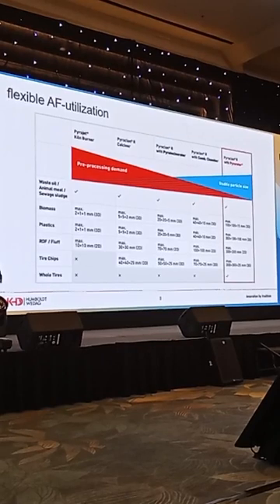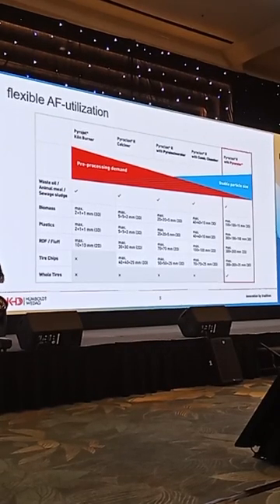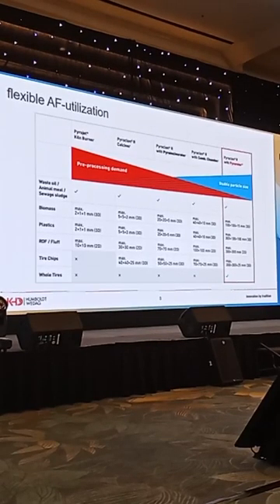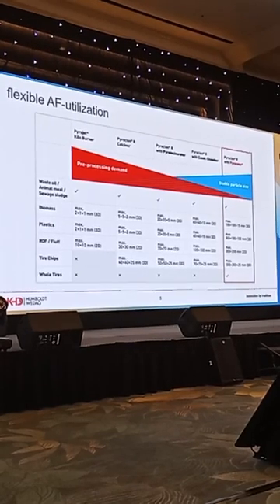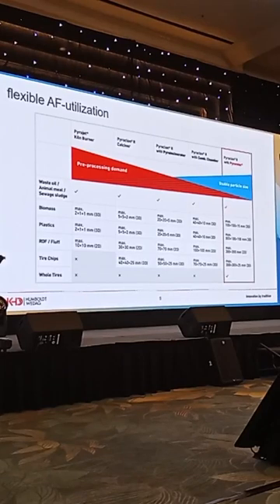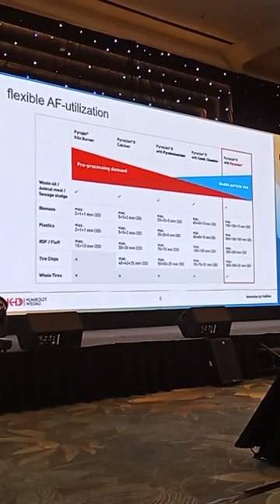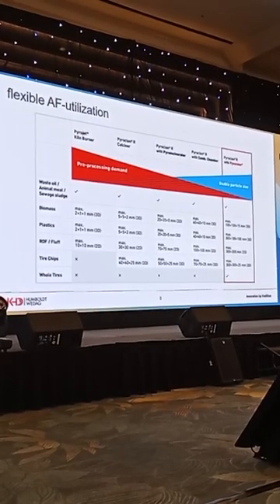So we are talking here about sizes of 20 to, let's say, 50, 70 millimeters, just depending on the alternative fuels you want to use. And finally, we have the newest development. This is our pyro-rotor system, where we are nearly unlimited to feed alternative fuels in very different sizes. You see, there's no problem to have material with 100 or even 300 millimeters of size. This depends mainly on the conveying system and the feeding system you're using to feed the material to this pyro-rotor, and even complete tires. Car tires, even truck tires, but truck tires, I have to say, have to be cut in smaller pieces, not really small pieces, but smaller pieces, but complete car tires can already also fit into this pyro-rotor.